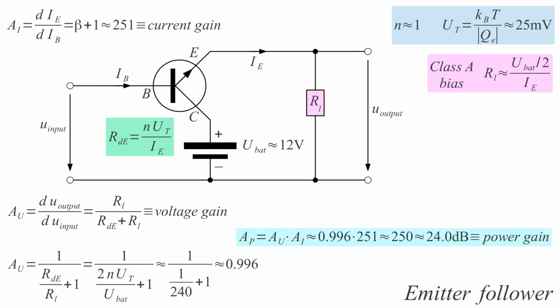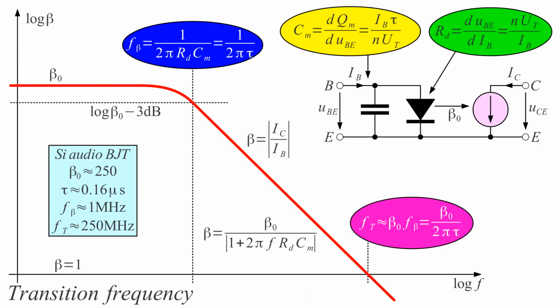This FT may go much higher than here. 250 megahertz is used for the transistor. Tau, the lifetime of the minority carriers, 0.16 microseconds with suitable doping. And we get F beta around 1 megahertz. So above 1 megahertz, beta of conventional silicon transistors is going to decrease.